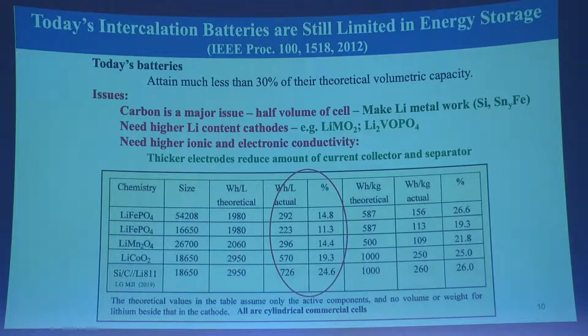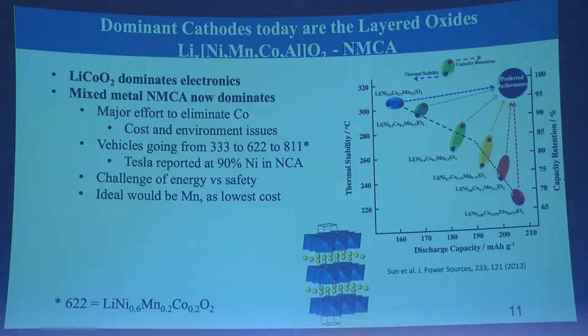It means we've got to get most of the graphite out. We've got to get more lithium into these materials. And ideally, we've got to make the electrodes thicker. Remember, every battery, you need a current collector to take the electrons in and out. You need a separator in between. So we can make the electrodes, say, double the thickness. We can take half of those current collectors, half those separators out. But they've got to be sufficiently conductive, both for electrons and lithium ions. So we're working on that.